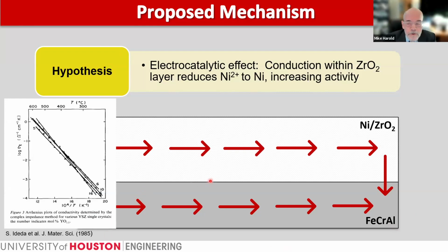Now, why do we say that? Well, zirconia is actually in the class of semiconductors. It has a conductance, shown here in some data from the literature, an Arrhenius plot of conductance versus 1/temperature that is activated. So increasing temperature leads to higher electrical conductivity of zirconia, unlike alumina, which is more of an insulator. So what we believe is happening is as we increase the power to the underlying FeCrAl, when we reach a certain temperature of the catalyst wire, and hence the top layer, the zirconia becomes somewhat conductive, enabling electrons to flow through it, which contacts the electrons with the nickel cations.